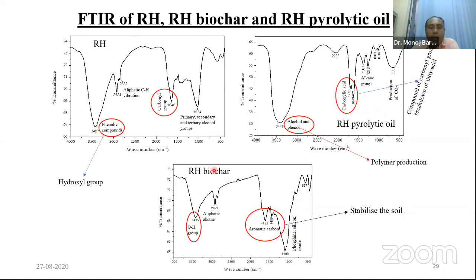And if we look at the solid product such as the biochar obtained from this rice husk biomass, we get some peaks around this 3400, similar to this, but again its intensity is quite lower in comparison to the biomass peak, and obviously it indicates the presence of hydroxyl group.